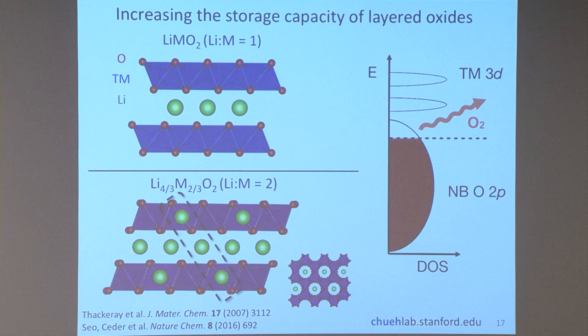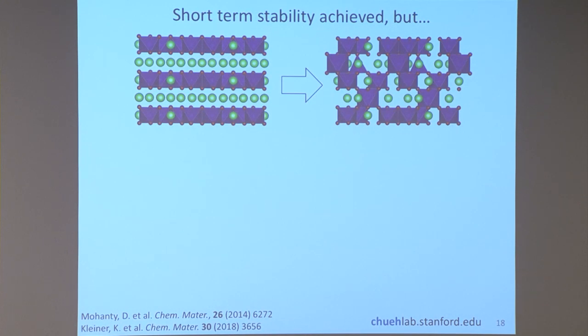So this has shown to be effective, but we don't understand how it works, okay? This is a very highly debated question in the field. In this material, we have achieved short-term stability, but in the long term, the atoms are still moving. But what is very interesting is you're not losing any of the energy capacity in the material. You can actually keep most of it.